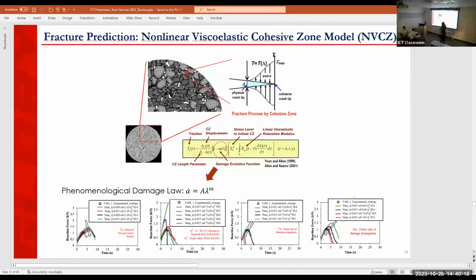For that, we can use what we call cohesive zone models, and there are many cohesive zone models published, available in the literature. We used in this study the nonlinear viscoelastic cohesive zone model, whose mathematical description is this big equation. We have the convolution integral here, embedded in the model. That's why it's a viscoelastic model. It's nonlinear because if you see the relationship between the traction and the displacement, you have a nonlinear curve.